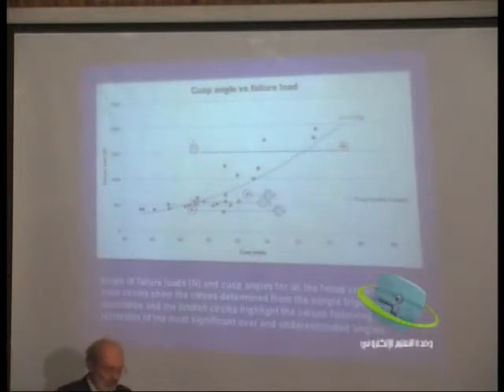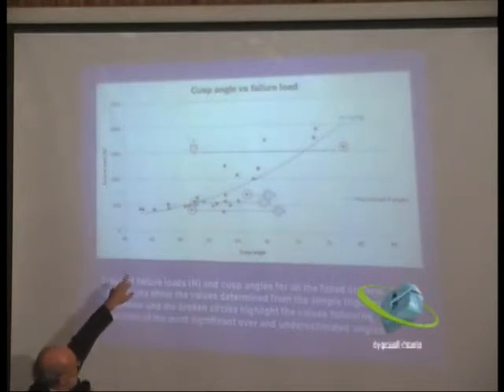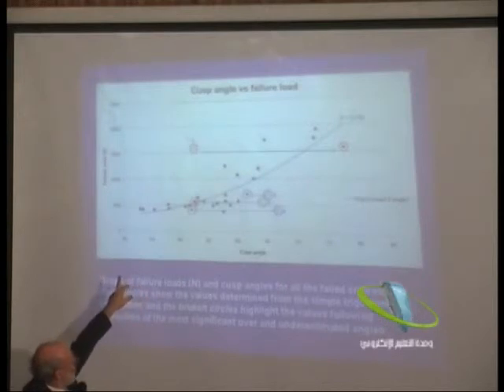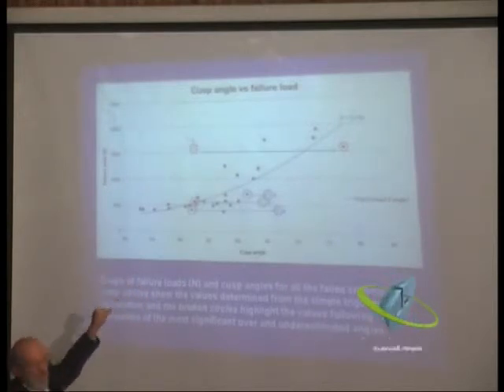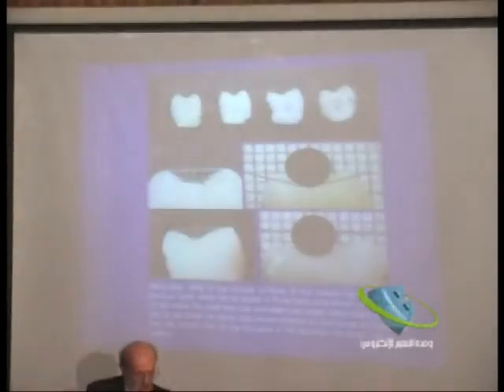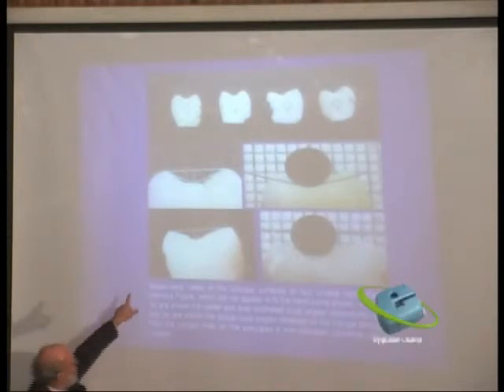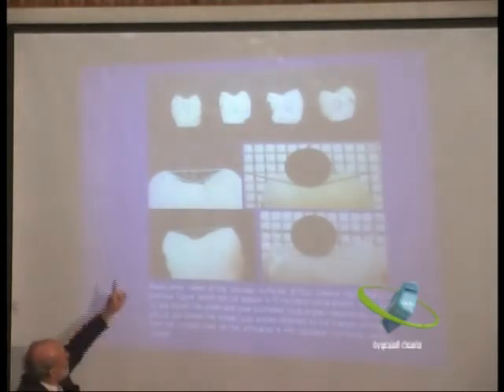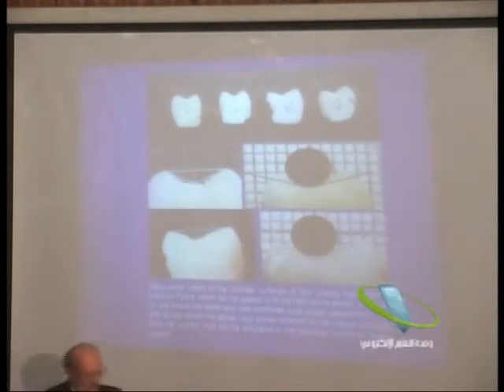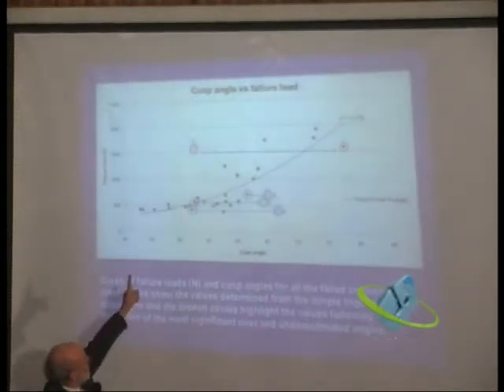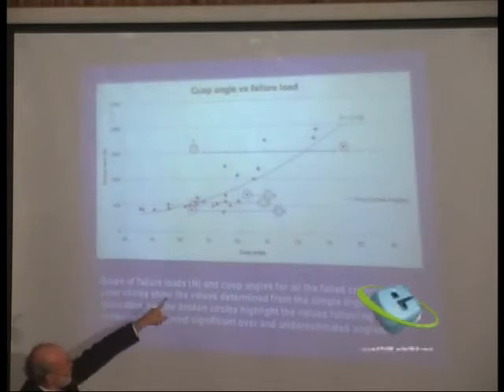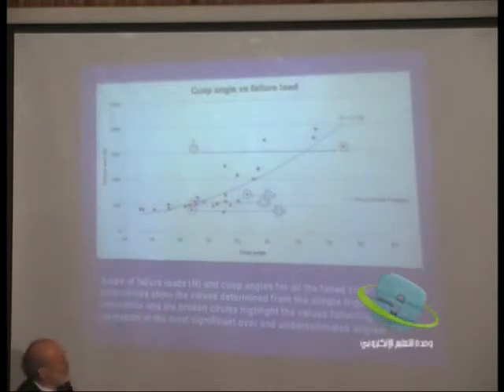Secondly, we started to look more critically at some of these samples, these ones that are in coloured circles. Initially, when we made the calculations, it was the cusp angle, the value that we had in the circles. And then we re-looked at some of those materials, and you can see here, this is how we calculated the angle, but when we looked in more detail, we could see that this was, in fact, a totally inappropriate calculation of the angle because the angulation was very different. So these were the 4 different materials we looked at, and on the basis of that, when we recalculated, we moved the samples in the direction of the arrow. One of them moved very much to the right, and the other 3 moved very much back to the left. So we got a very neat relationship between the failure load and the cusp angle for all of these materials.